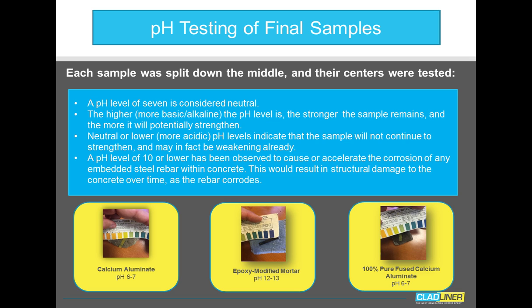Now, another interesting factor is that it has been determined that a pH level of 10 or lower, which would still be considered very basic and would still be considered pretty good for the sake of the concrete itself, would, however, still result in the acceleration of the corrosion of any embedded rebar within the concrete. Okay, so if the pH is 10 or below, the rebar within the concrete still has the tendency to want to corrode.